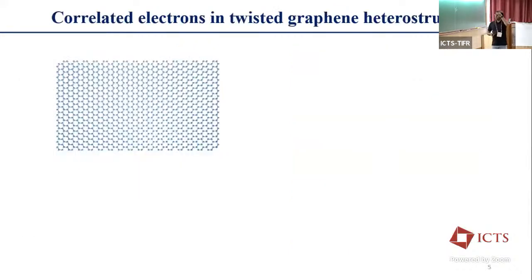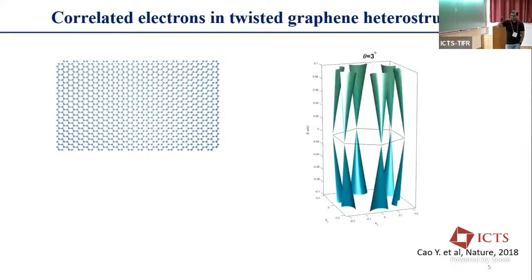For example, if we stack 2 different graphene layers and we make a particular twisting angle, then we really change the band alignment. And if we are really lucky enough to stack them at a particular angle, which is 1.1 degree, then we end up with a flat band. And then if we keep increasing the twisting angle, then we really end up with the properties of graphene.